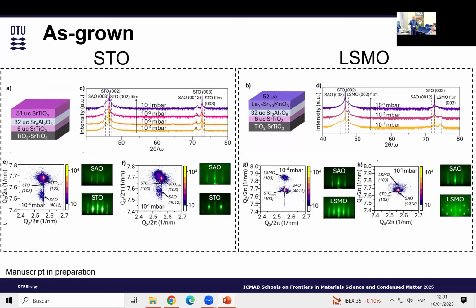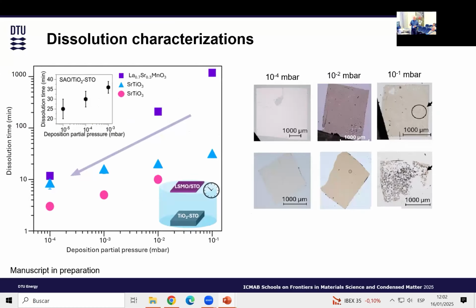And some of the results that you see, I'm not going to go through all the results, but we can see that at different pressure, for example, this one, 10 to the minus 1. This is for LSMO. If you grow it at 10 to the minus 1, the LSMO will go not layer by layer, but as an island. So is the STO, if you grow it in another condition. Keep in mind that the SAO has 10 to the minus 4. So we looked at the material from the structural point of view, but what we characterize here is the dissolution time as a function of deposition partial pressure. So what we see is that there is an increase in the dissolution time as we reduce